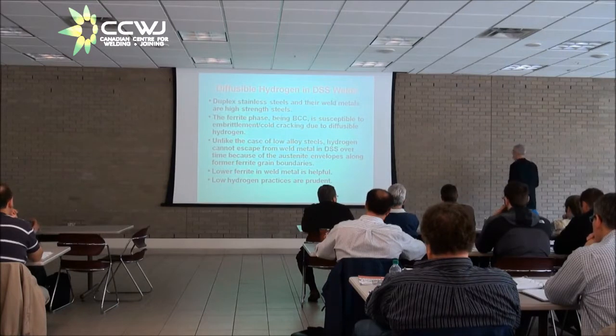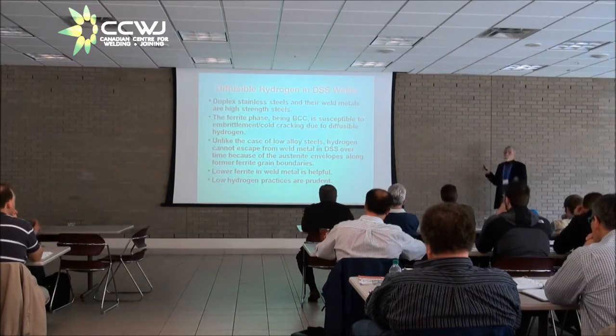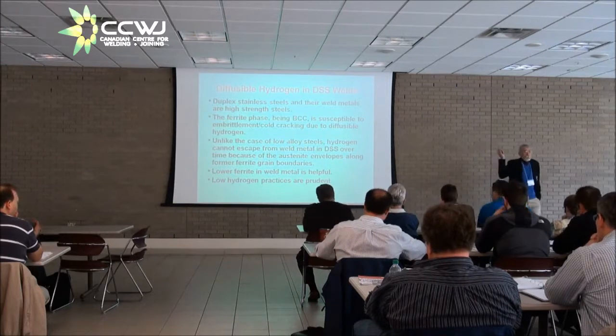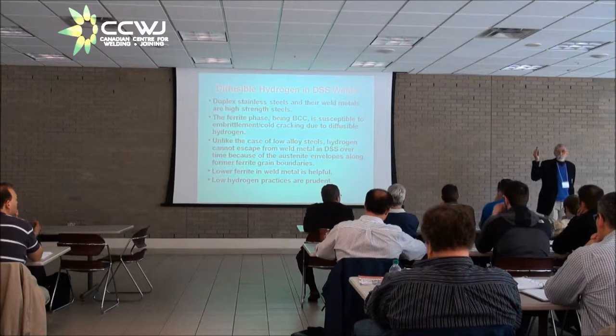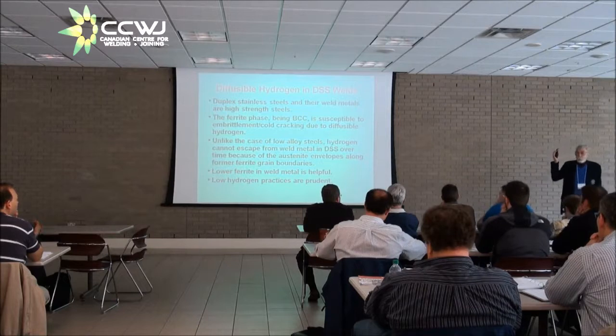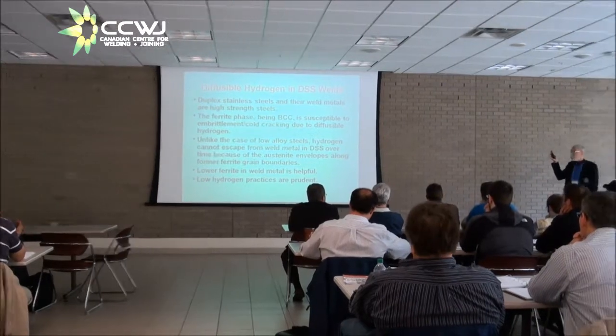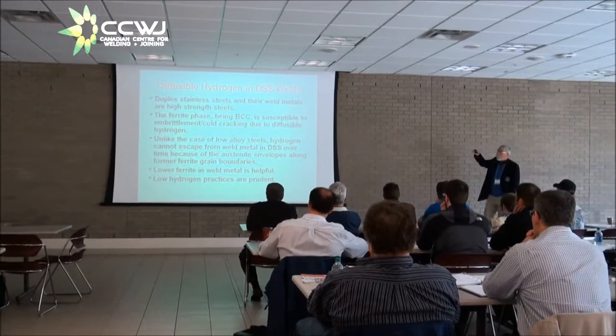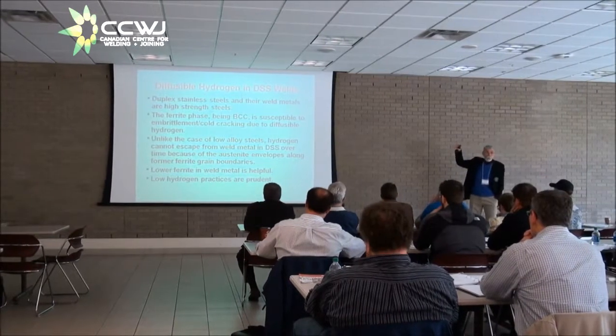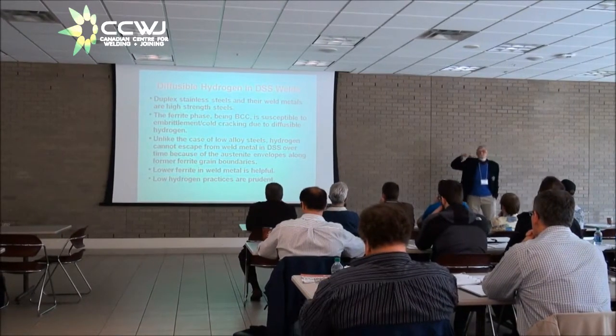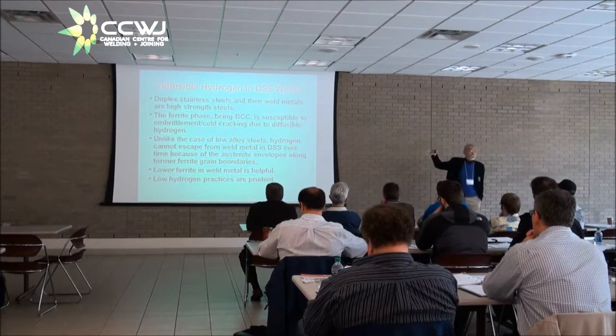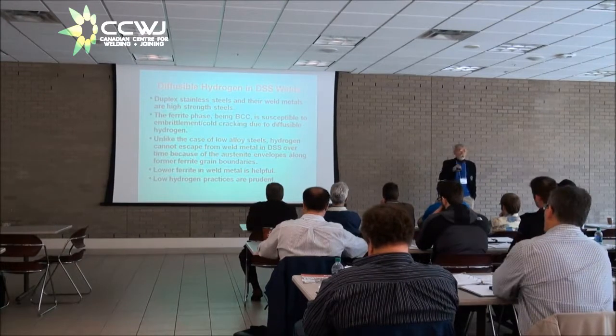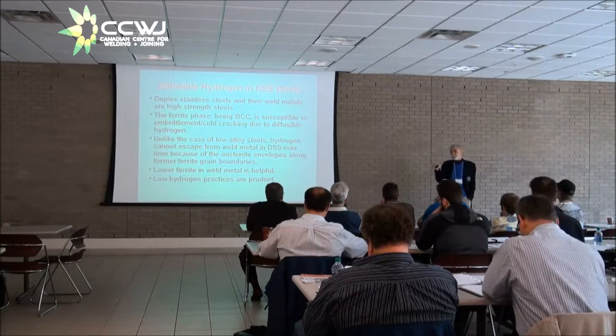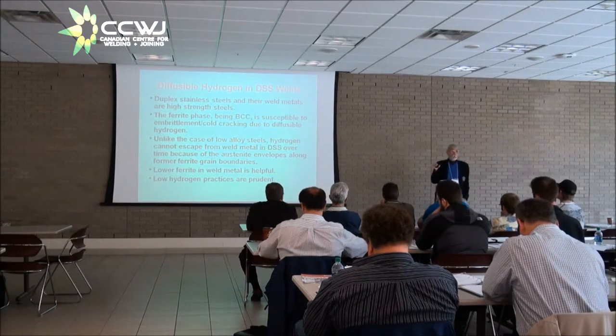Now, one other thing that hasn't been mentioned yet is diffusible hydrogen in duplex stainless steel. It's stainless. You don't have to worry about diffusible hydrogen. The hell you don't. You have to worry about hydrogen in duplex stainless steel, especially when the ferrite content gets high. You know, the specifications will tell you, oh, you can use 30 to 70% ferrite. If you got 70% ferrite and you got appreciable diffusible hydrogen, you're going to have a problem.